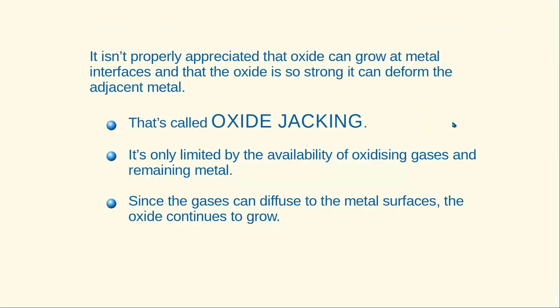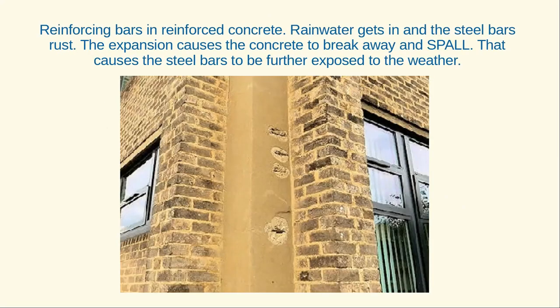So again, it isn't properly appreciated that oxide can grow at a metal interface, and the oxide is so strong it can deform the adjacent metal. That's called oxide jacking. It's only limited by the availability of oxidizing gases and remaining metal. Since the gases can diffuse to the metal surfaces, the oxide continues to grow. Here's a photograph I took myself a while back. Reinforcing bars in reinforced concrete. Rainwater gets in and the steel bars rust. The expansion causes the concrete to break away and spall. It's called spalling. That causes the steel bars to be further exposed to the weather.